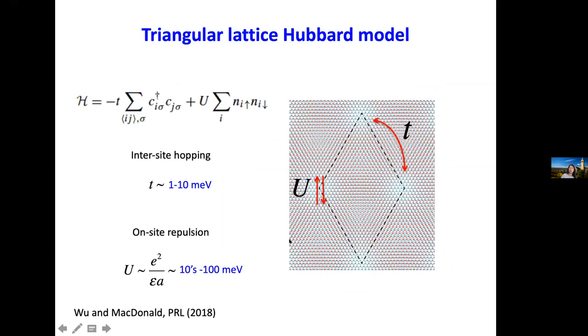Okay. It has been shown by Allan MacDonald and his student Fengcheng Wu a while ago that the system can be described by a single band Hubbard model with two parameters: the on-site Coulomb repulsion, which was estimated on the order of 10 to 100 meV, and also inter-site hopping, which is on the order of 1 to 10 meV. And this hopping parameter decreases exponentially with decreasing twist angle.